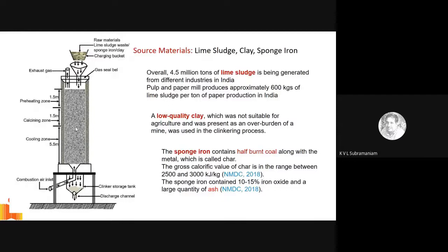And then the calcium has to fuse with the silica to produce these calcium silicates. So that process was enabled in this vertical kiln. The source materials that we used, remember I had said that we were planning to produce this cement from 100% waste. And what we used as our raw materials were lime sludge, clay, and sponge iron.